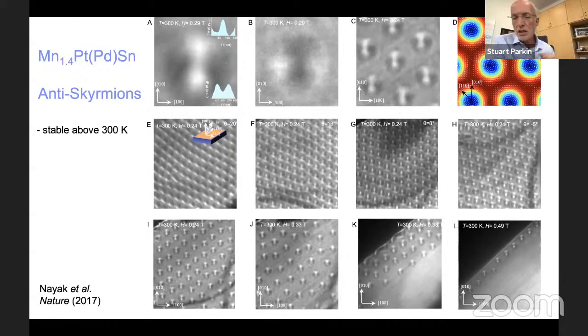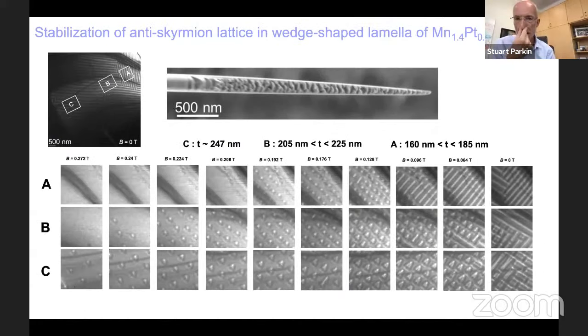I don't want to again discuss that in too many details. I want to discuss just one aspect of these anti-skyrmions, and that is how the anti-skyrmions evolve, firstly, from a helical magnetic structure. So if you look here, what are we looking at? In the top left, you can see, again, a Lorentz transmission electron micrograph for a wedge-shaped lamella, which we've fibbed from a single crystal of this manganese 1.4 platinum tin.